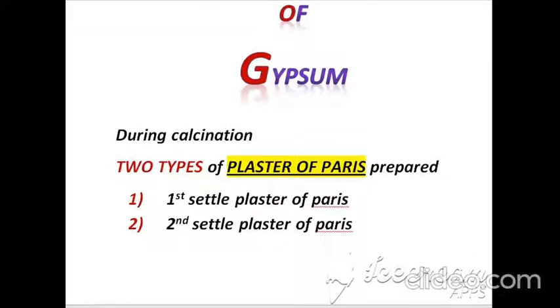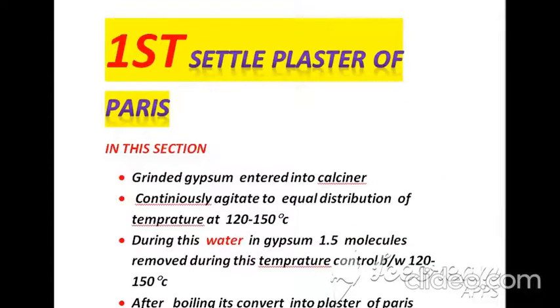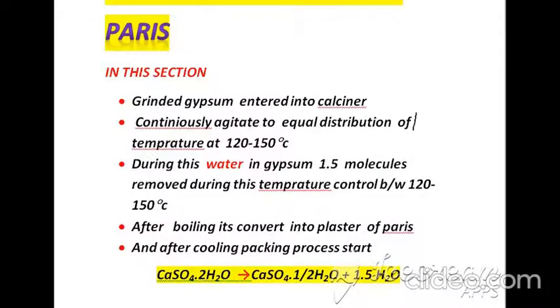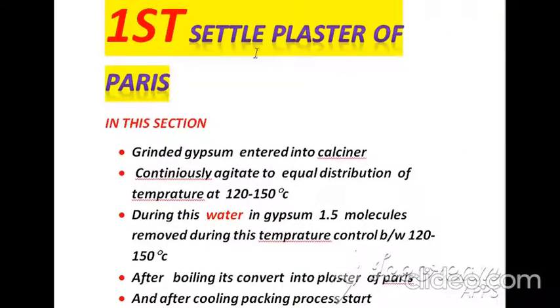During calcination, two types of Plaster of Paris are prepared. The first one is first-settle Plaster of Paris. Ground gypsum is entered into a calciner where it is agitated continuously, and the purpose of agitation is equal distribution of temperature. During this heating process, approximately 1.5 molecules of water are removed from gypsum. Temperature is controlled between 120 to 150 degrees centigrade. After boiling, it converts into Plaster of Paris, and after cooling, the packing process starts, giving us first-settle Plaster of Paris.